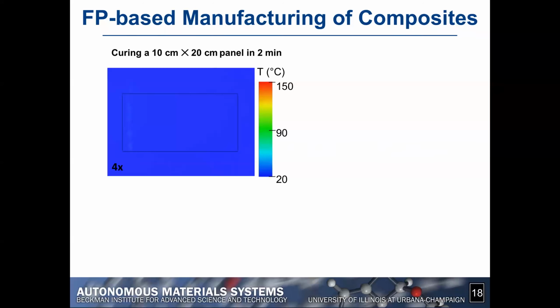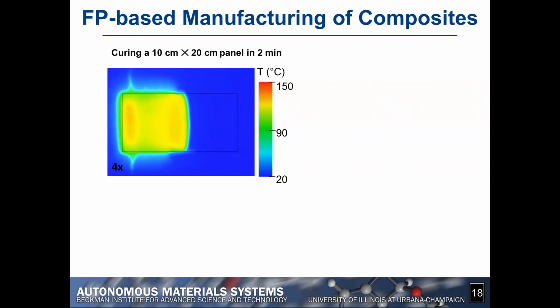So what you're going to see here is the evolution of the temperature. This is an actual experiment using an infrared camera for a fairly small, 10 centimeters by 20 centimeter panel. We introduce a little bit of heat using an embedded wire, then we just turn it off, and you can see that the front starts to propagate in a steady fashion through the entire part. We managed to cure this entire panel in about 2 minutes, once again, to be compared with the multiple hours that you may need if you use a conventional bulk polymerization technique, right?